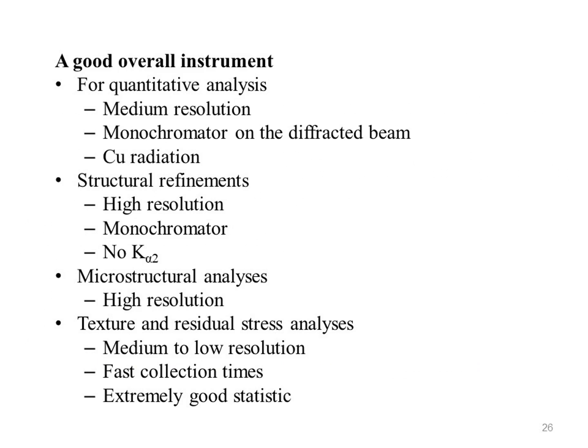A good overall instrument for quantitative analysis: medium resolution, monochromator on the diffracted beam, copper radiation. Structure refinements or structure determination: high resolution and high intensities, very long collection times. Monochromator, no K alpha 2. Microstructural analysis: high resolution. Texture and residual stress analysis: medium to low resolution, fast collection times, extremely good statistics.